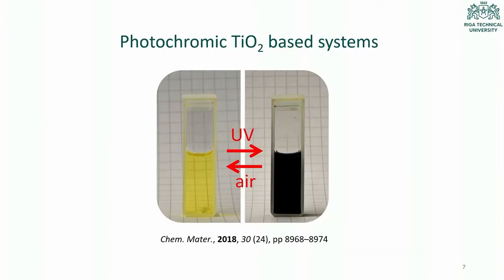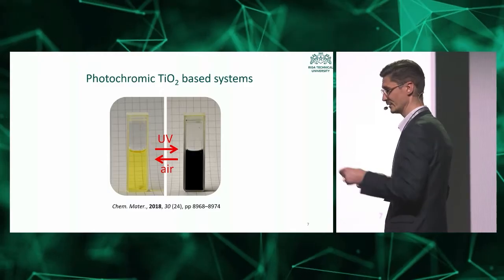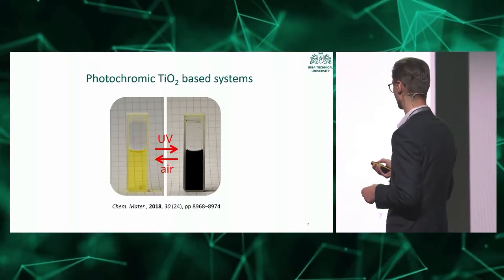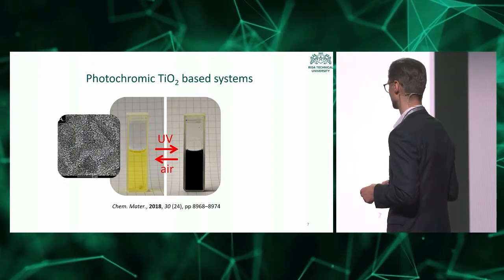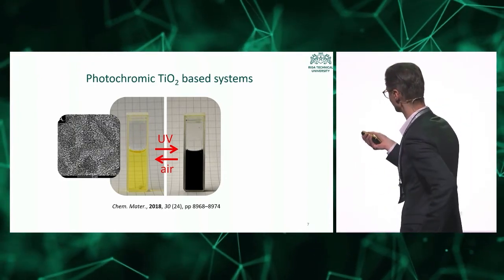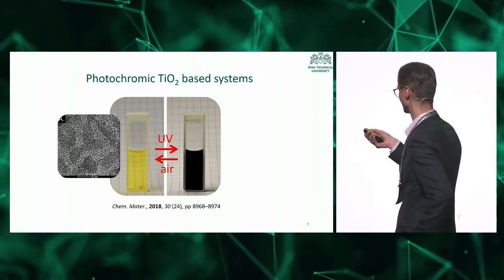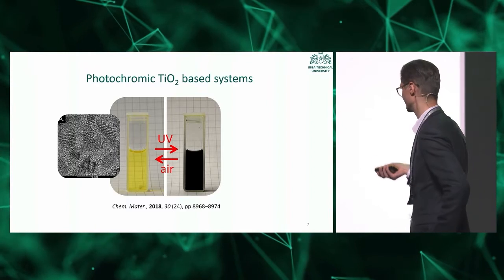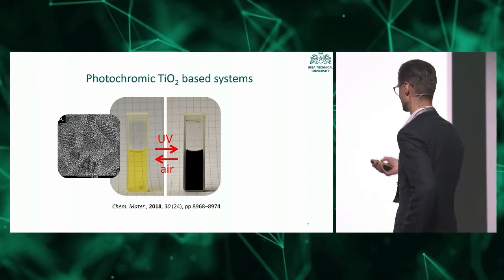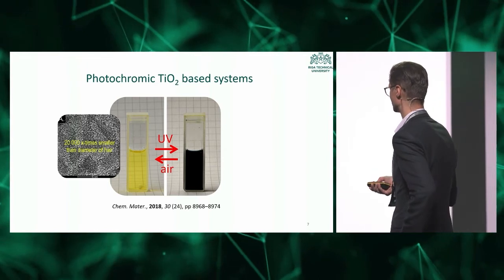And yes, we started in 2018, or actually earlier, when I was spending my time at the University of Tartu, where we developed photochromic titanium materials which change their color when you irradiate them with light. As you can see, it turns pitch black, and you can turn it back to white. The transparent liquid is actually composed of solid nanoparticles, but they are so small that they don't scatter the light, and it looks like pure water. They are really small, about 20,000 times smaller than the diameter of a hair.